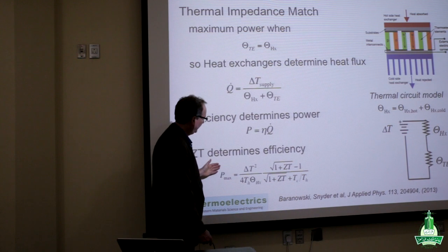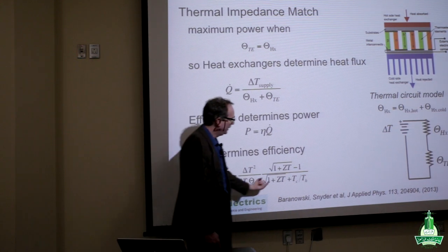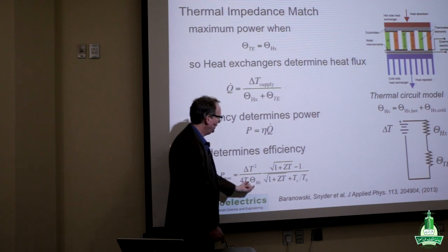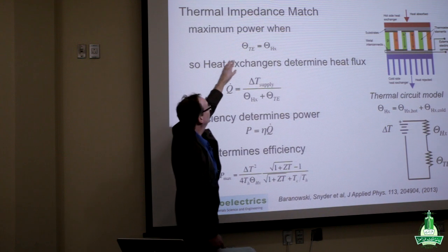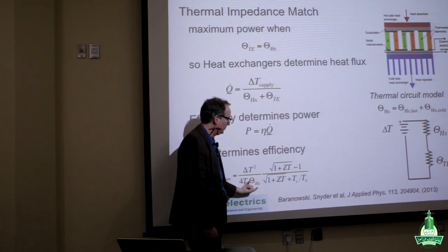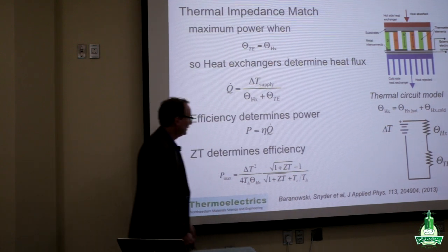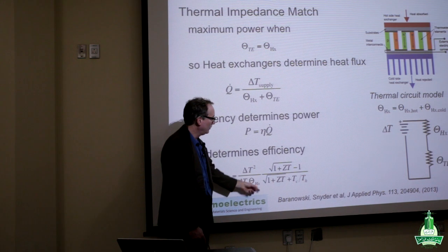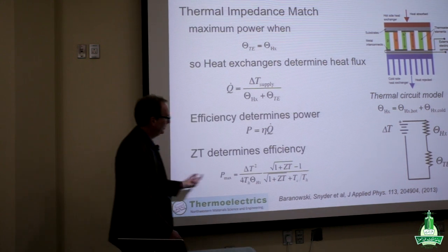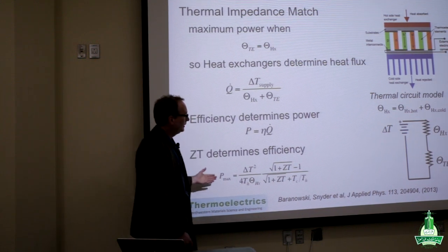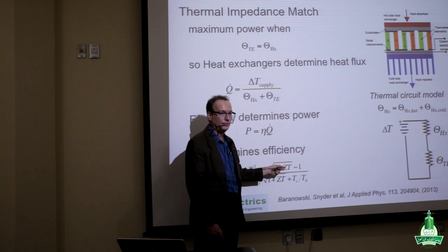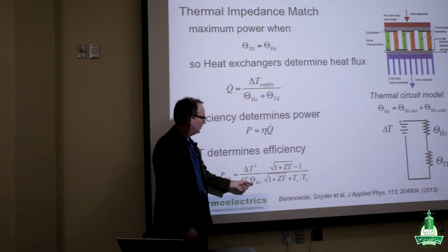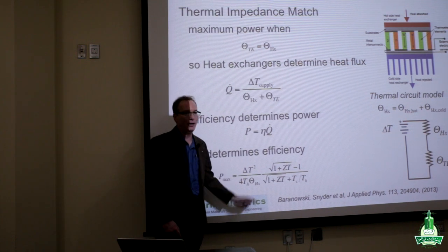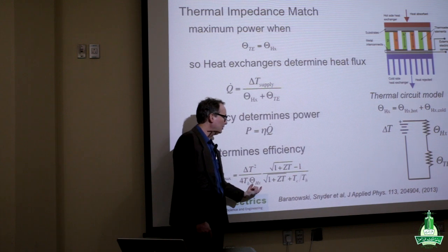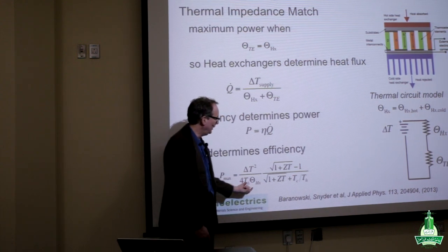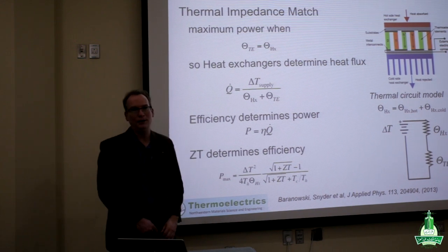So we are left with a relationship where our maximum power comes from our ZT parameter from the efficiency, and then through the thermal impedance matching, it says that our thermoelectric should be sized to be equal to our heat exchanger thermal impedance. Tells us that we will get the maximum power when we have our best designed heat exchanger. And so what this means is that, yes, we spend quite a bit of time optimizing ZT, but we would get just as much improvement, perhaps even more, by optimizing heat exchangers. And making these heat exchangers more efficient and less costly is going to directly impact our power.